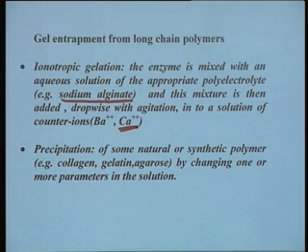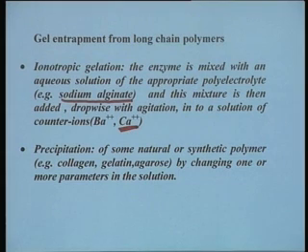Of course, one of the disadvantages here is the stability of these materials. For example, calcium alginate, although insoluble in aqueous medium, gets solubilized by certain ions like phosphate ions. If your medium contains phosphate ions, calcium alginate will slowly get dislodged, and you will end up with dissolution of the immobilized preparation. Very often, barium or aluminum is used instead of calcium as a counter ion, and such methods are very commonly used, not only for enzymes, but even for other biocatalysts like whole cells. This method provides a very viable method for immobilization.